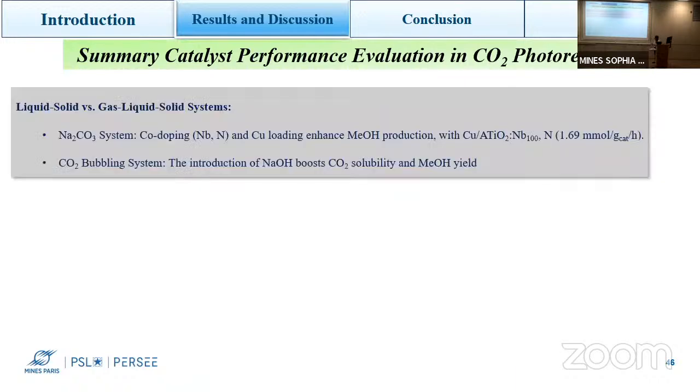And now we summarize our performance. With the liquid-solid system and the gas-liquid-solid system, which is the sodium carbonate and CO2 bubble system, we compare each other. We can see our co-doping and the loading both enhanced methanol production, and we also get one of the best catalysts. For the CO2 bubble system, the solubility is the key to improving its methanol production.